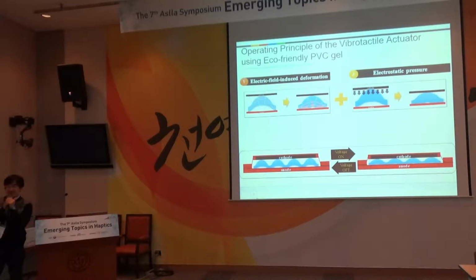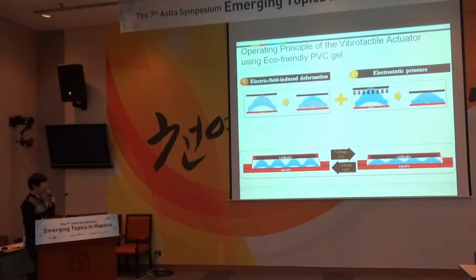This structure has a great advantage for making the haptic vibrotactile actuator. The reason is that two energies are merged in the actuator. The first energy is caused by the electric field induced deformation, the characteristic of the ePVC gel moving to the anode, like I said before. And then, due to the parallel electrode, there is electrostatic force. So we can maximize the vibrotactile performance.